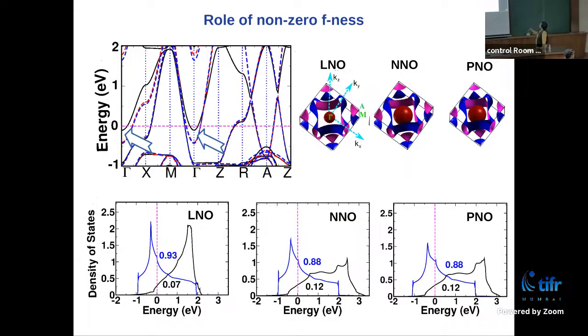So we did the calculation for neodymium as well as for praseodymium, and lanthanum I showed you already. We find, both for neodymium and praseodymium, this electron pocket, which was given by the second orbital, namely the axial orbital, they are exactly the same. So that means it's the empty 5d that matters, not really the 4f. But 4f has a role because in case of lanthanum, there is no f electron. If I put some f electron, that actually pulls down the energy position of this empty 5d level, and therefore its interaction with the nickel becomes different. That's the role of the 4f. It's just a Madelung energy, if you like.